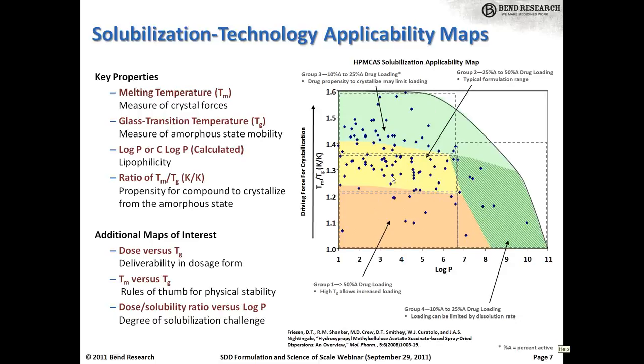And then in the other parts of the map, you get into more middle-of-the-road compounds in terms of lipophilicity and crystalline forces, and there oftentimes you can increase the drug loading to 25, 50% and still have good performance and stability. So we use maps like this and a number of others that are called out on the bottom left. I won't read them off, but the point is you can leverage fundamental understanding of the science behind dispersions, as well as empirical experience in formulating, to screen a fairly small number of formulations to select one that's going to give you acceptable performance and stability, rather than screening a very large number. So that's a good way to proceed as a paper exercise before beginning formulation.